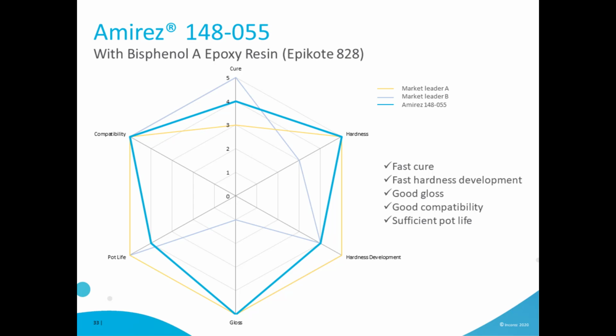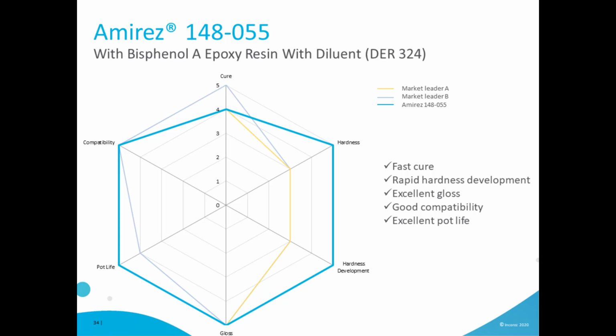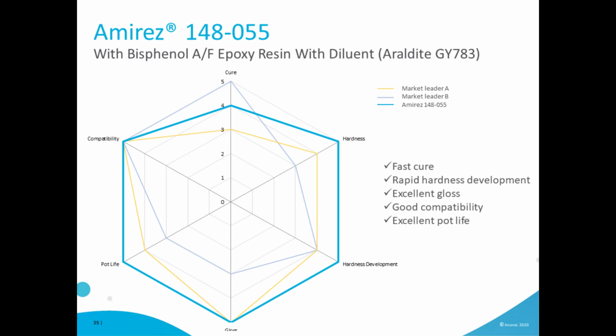So we have here the comparative results with the different types of epoxy resin. First one being bisphenol A epoxy resin Epikote 828. You can see here that our product in blue gives a fast cure, good gloss, good compatibility with a decent pot life. Results are getting even better for BPA with diluent like DER324 with a very fast cure, rapid hardness development, still good gloss, good compatibility, and slightly longer pot life. Some of the best results are then achieved with BPA/F with diluent.